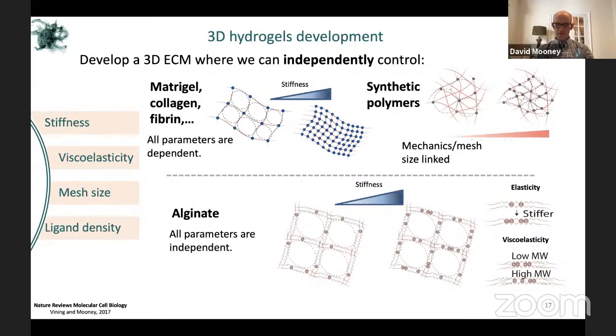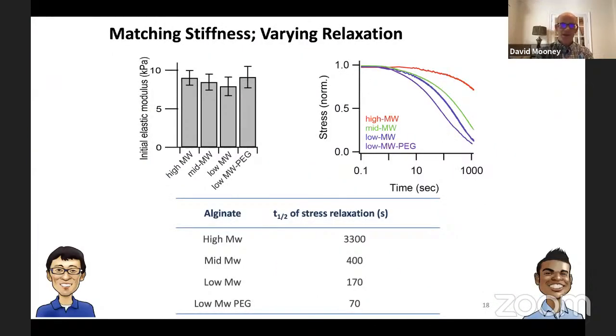Further, we can independently vary the viscoelasticity versus the stiffness by controlling the molecular weight of the polymer chains, which allows us to alter their relative mobility and thus their ability to dissipate stresses independent of stiffness and these other variables. So here's just an example of a group of hydrogels that Ovijit Chaudhuri on the right, who's now running his own lab at Stanford, and Luo Gu, who's running his lab now at Johns Hopkins, demonstrated a few years ago, where you can see from the top left that these 4 gels all have very similar initial elastic moduli, but on the right, you can see that they have varying rates of stress relaxation, which we've characterized by the half time for stress relaxation on the bottom. And you can see that we get a couple orders of magnitude variation in the stress relaxation behavior while we keep the moduli similar or constant.